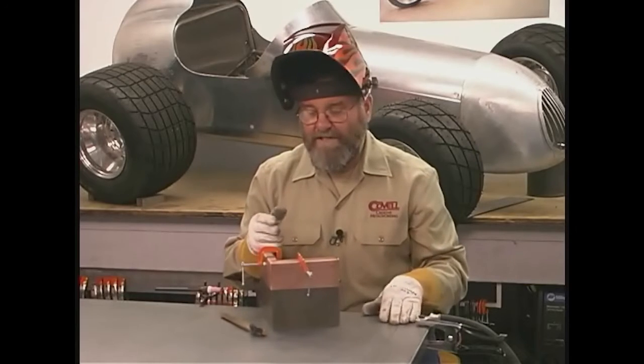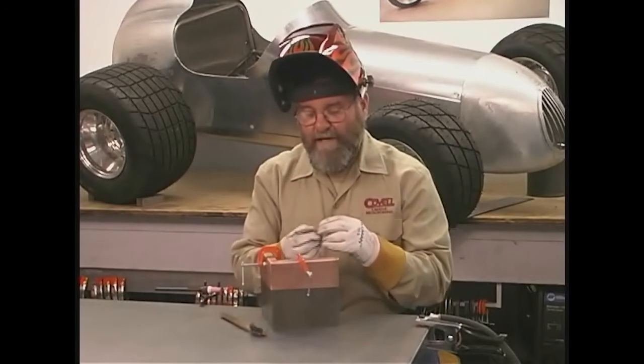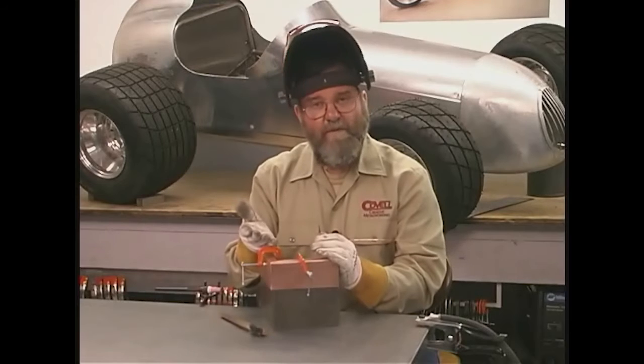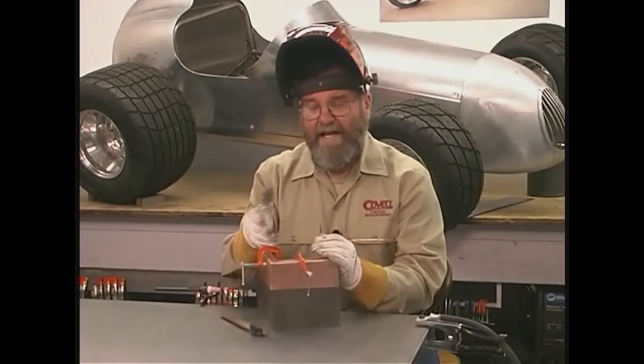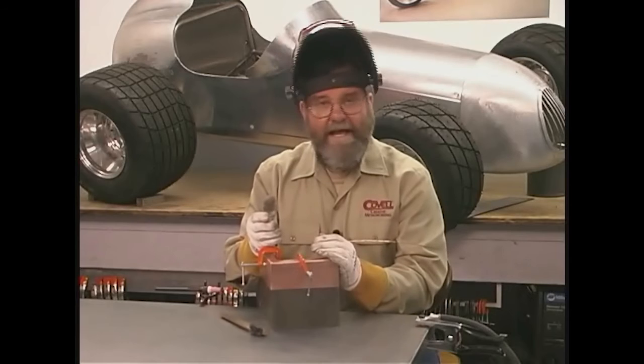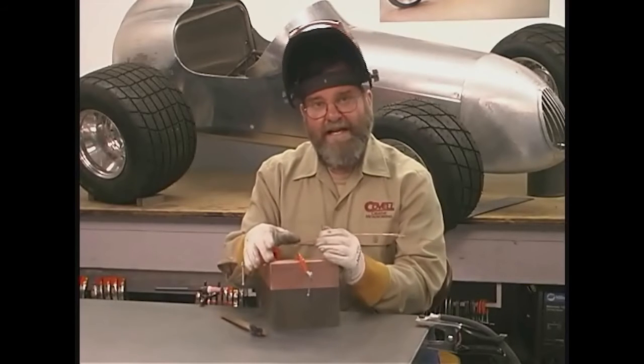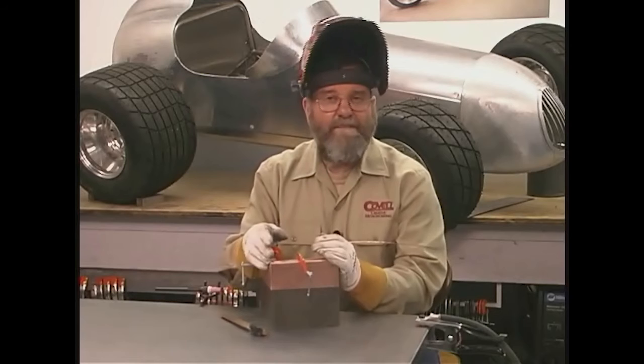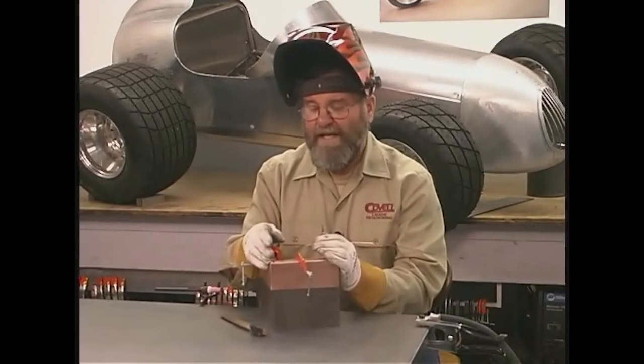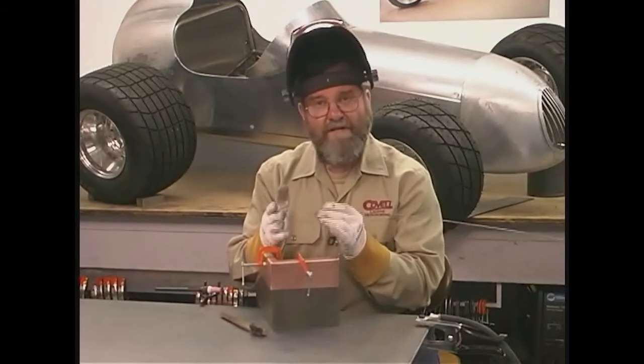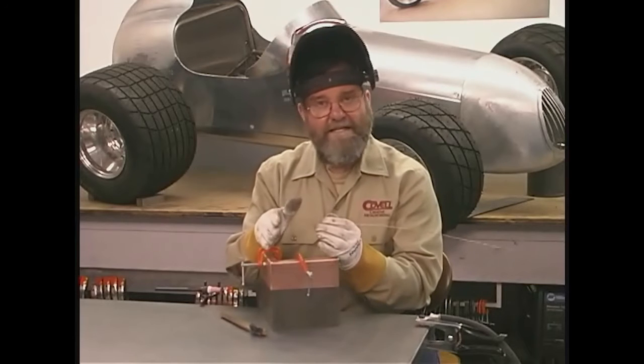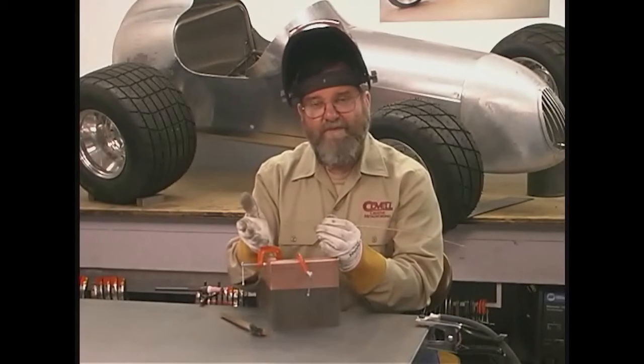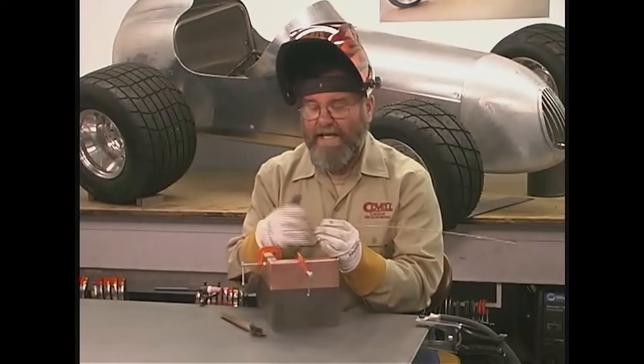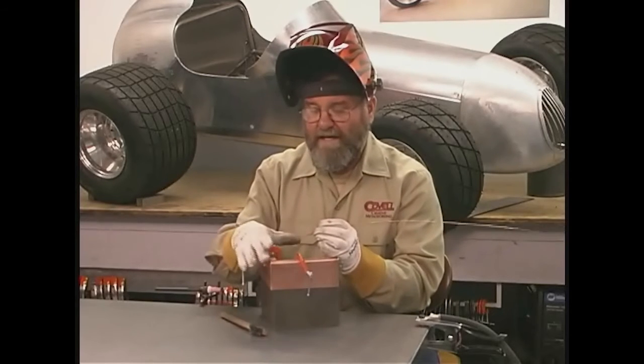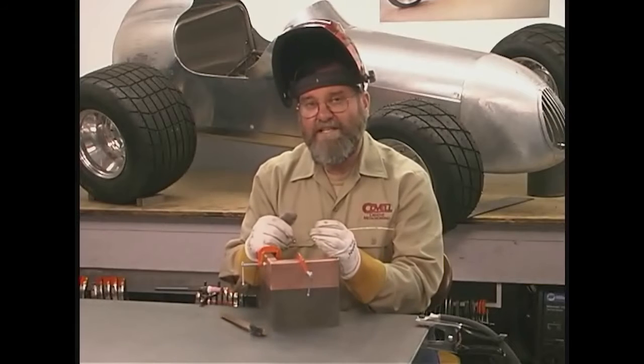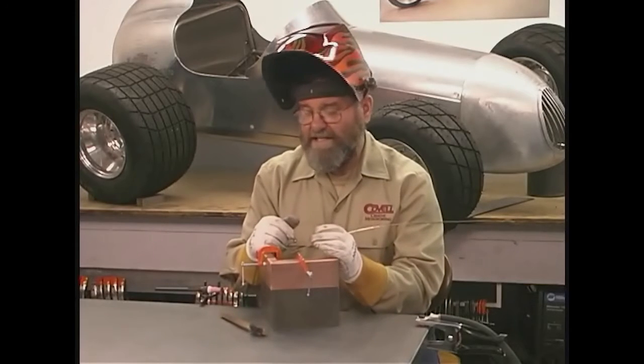So the first time I wanted to try it, I didn't know where to get the proper filler rod, so I got some electrical wire, stripped the insulation off of that, and used it for filler rod. It actually worked. I was able to form a puddle and add the rod to it and make a weld bead, but I got a bead with a lot of porosity in it. Later on, I learned that there's a special deoxidized copper rod designed for TIG welding. You can get that from many welding stores, or they can special order it. And using that rod solves the problem. Then you can flow a puddle that has no porosity. So it's a real nice clean process.